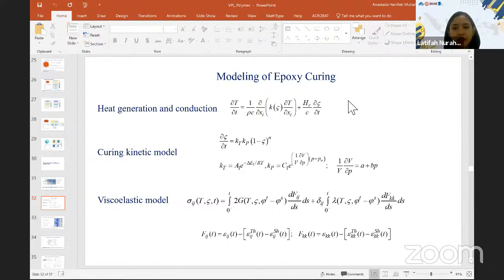And how do you think the cross-linking affects the viscoelasticity? What is your opinion about that? Well, the idea is that cross-linking is formed like a bond, right? So when you stretch or release it, unless it is breaking, you can stretch the polymer to a certain level. But when you look at viscoelasticity, the mechanism is due to the delayed response. The polymer has long chains, right? When all these long chains are entangled and you try to load them, it takes time until the molecular network comes together and reacts to external stimuli. That's where you see a delay in response.